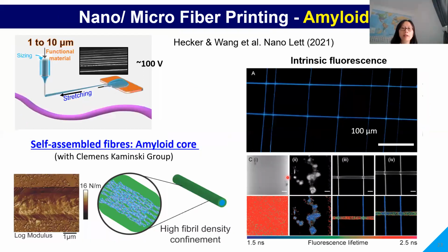Working with Clemens Kaminsky's group, we use our fiber printing process to guide the self-assembly and patterning of amyloid fibers. The structural control of these fibers is more challenging because amyloid fibers are constantly aggregating. Therefore, we designed a core shell flow nozzle to achieve controlled aggregation of the fibers. And we show that the fiber printing technique is able to retain the intrinsic fluorescence arising through the amyloid beta sheet protein folding structure.